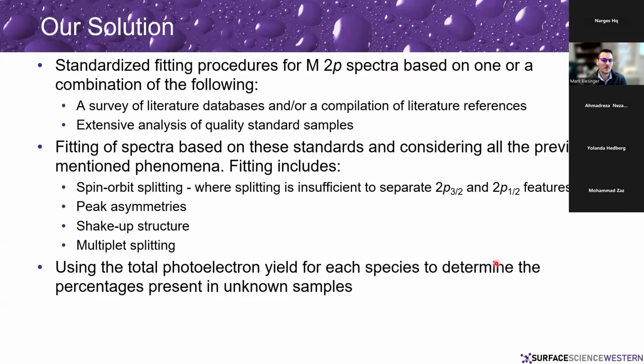We'll take into account peak asymmetries for the metal structures or conducting materials. Look at things like shake-up structures, and then we'll model a lot of the multiplet splitting to see that total peak shape. And we'll use the total photoelectron yield for each species to determine the percentages present in unknown samples.